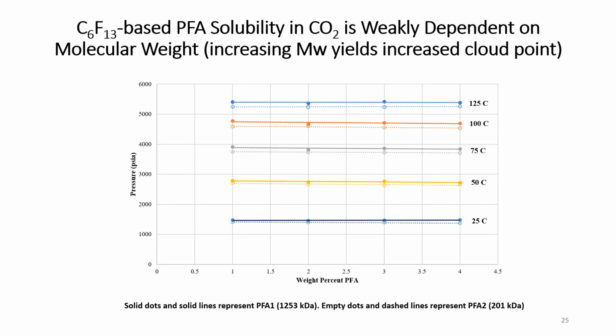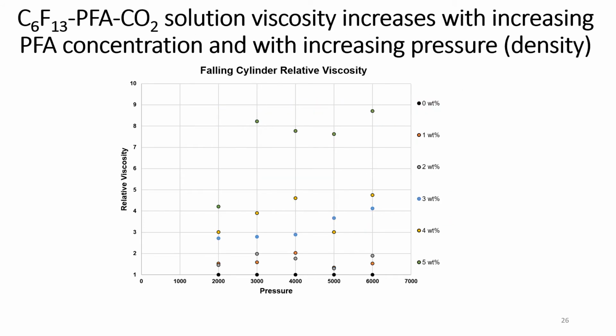We tested C6F13 solubility at 2 molecular weights, and as seen in previous experiments, the solubility is independent of concentration, but strongly dependent on temperature and weakly dependent on molecular weight. In the viscosity experiments, we also found the viscosity effects generally tended to increase with increasing PFA concentration and increasing pressure.